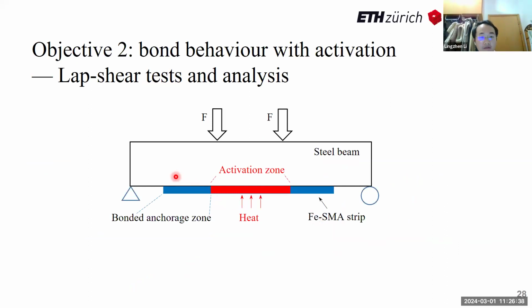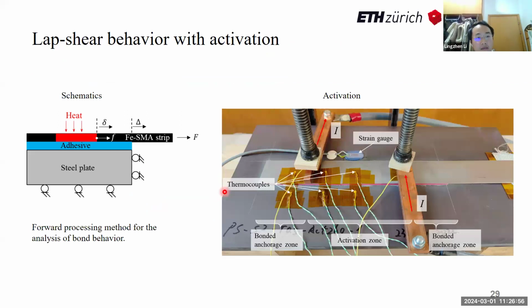Okay, so far we have gained some knowledge in the bonded anchorage zone. Then, what is the influence of the activation temperature and generated prestress on the adhesive bond? I designed such an activation setup based on this lap-shear model with local activation. In this special setup, copper clamps allowed electricity to enter the shape memory alloy from this location, go through the shape memory alloy and go out from this location. Only the center part of the shape memory alloy strip was heated and generated prestress.